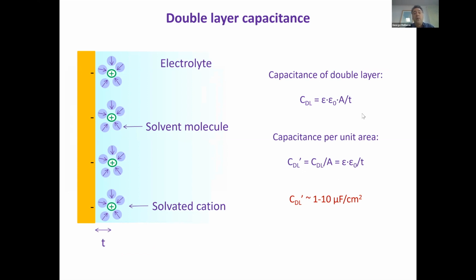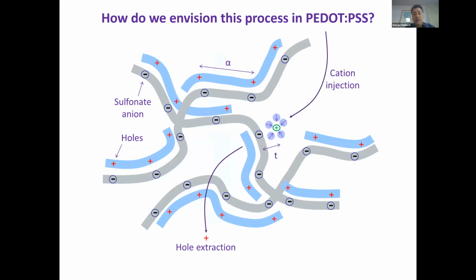We can understand using a toy model, starting from a Helmholtz model of a capacitor, where you have an impenetrable electrode with ions butting against it. You have a capacitance that, if you normalize it per unit area of the electrode, would depend on some dielectric constants, and then a distance, which is the center of the ion to the electrode surface, so that would reflect the solvation sphere of the ion. And uniformly, this has values across many different flat metal electrodes of the order of 1 to 10 microfarad per square centimeter.